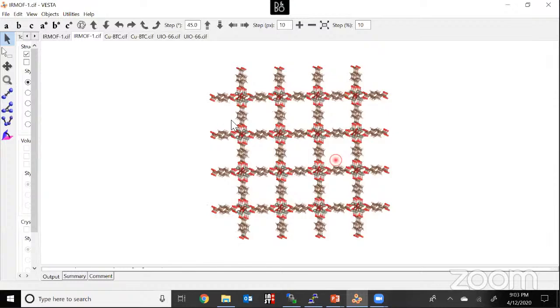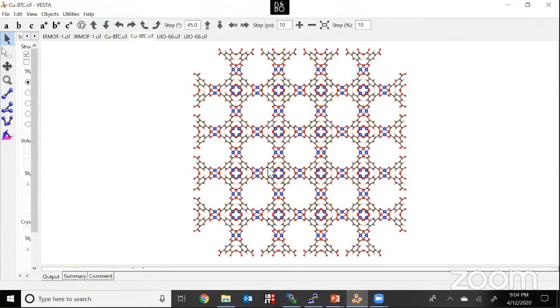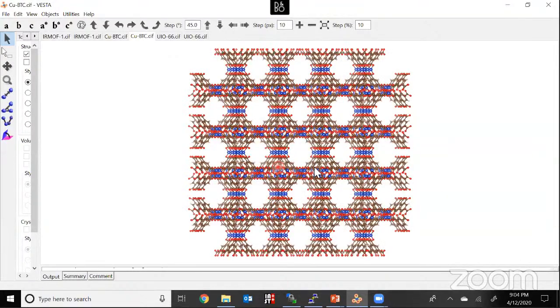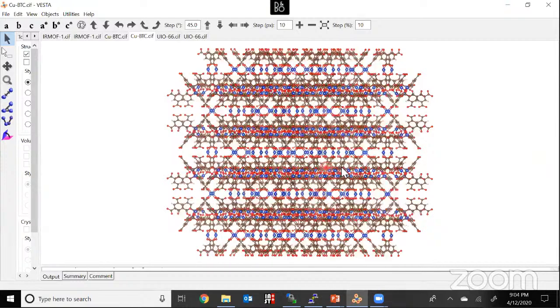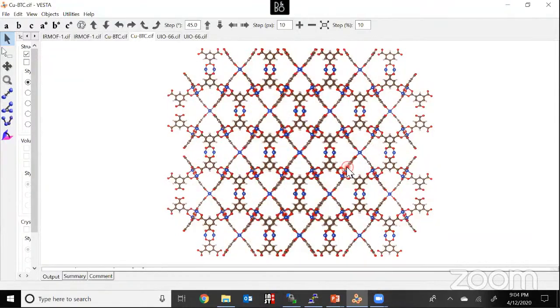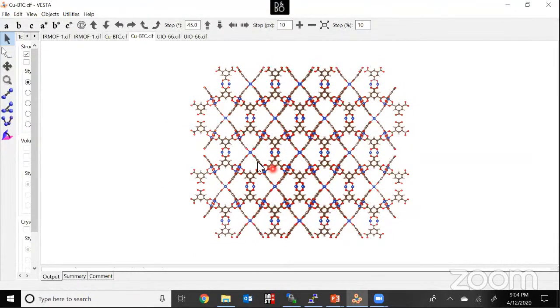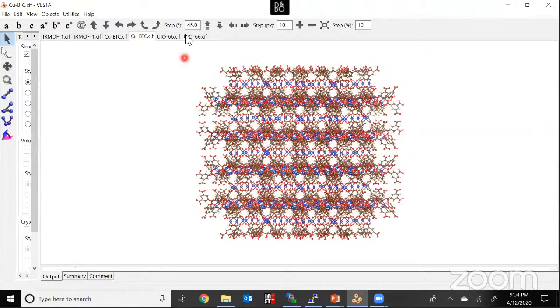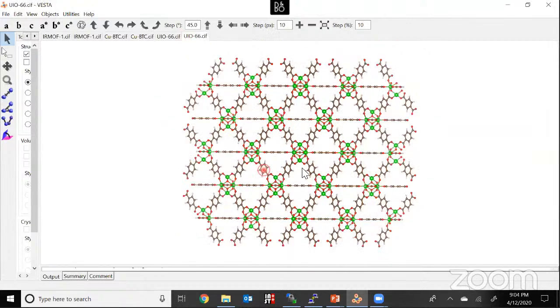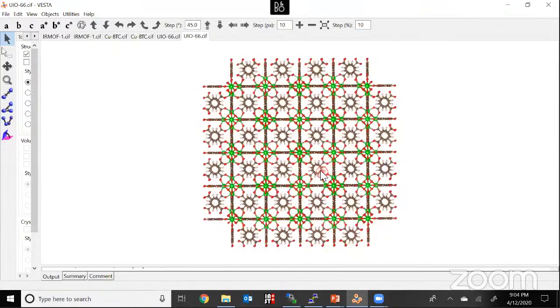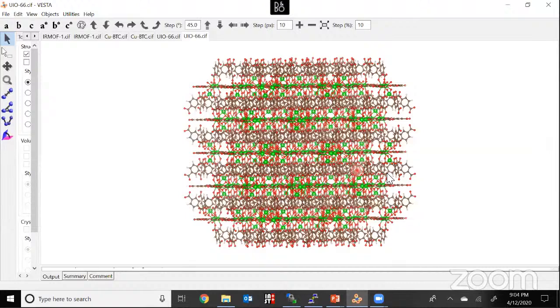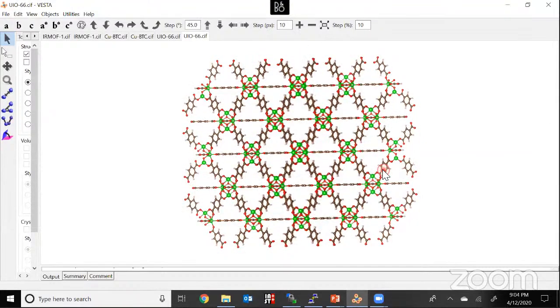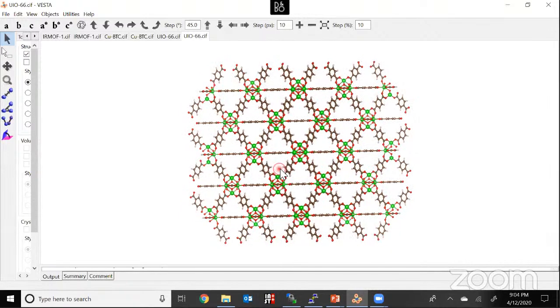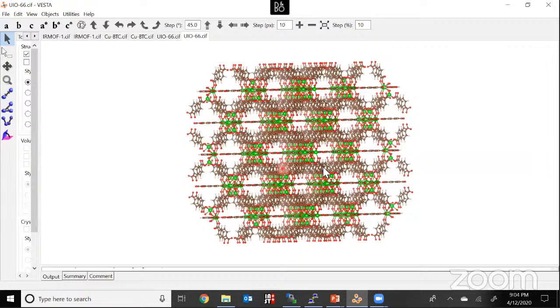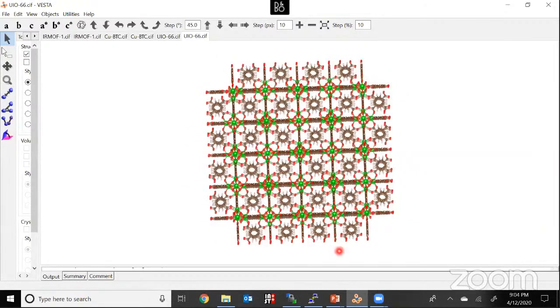This is MOF5, and this one is copper BTC. Here the connector is a copper paddle wheel type connector, which is connected to benzene tricarboxylic acid, forming this beautiful structure. And this one is zirconium oxide. These zirconium based MOFs are highly stable and highly useful for studies near room temperature. If you want to do some sort of study, we can use this MOF. These MOFs have their own applications as well.